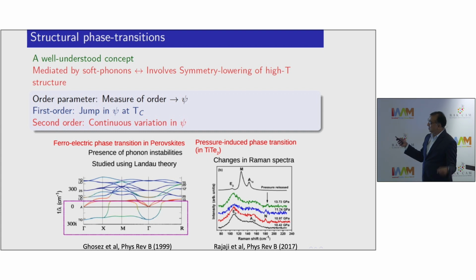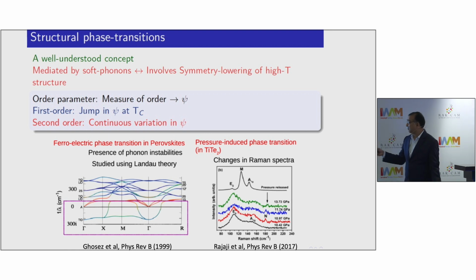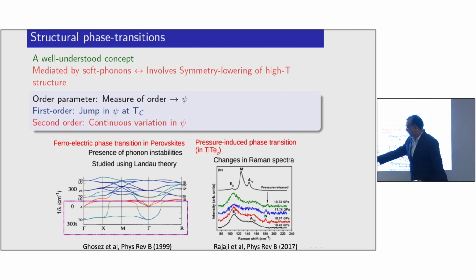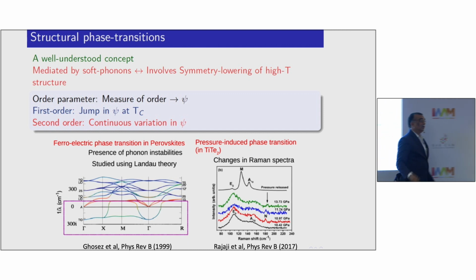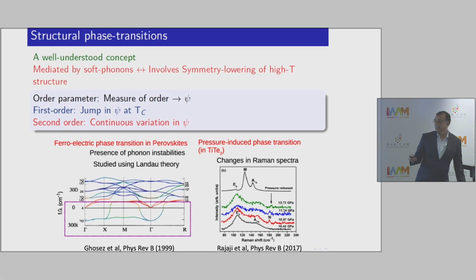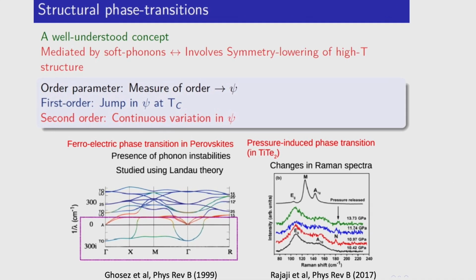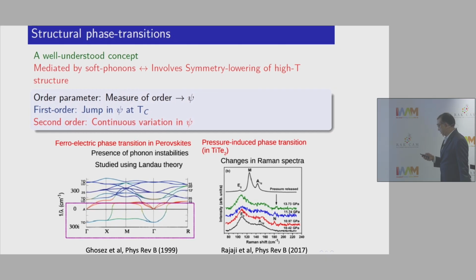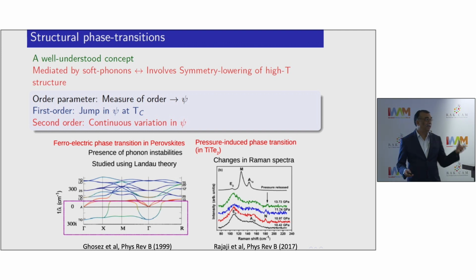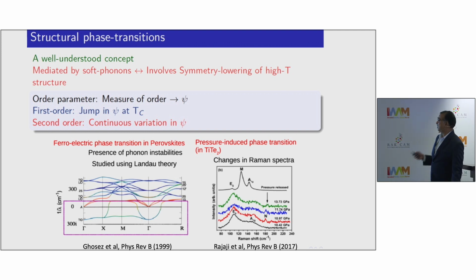If you look at very standard structural phase transitions, I'll quote here the ferroelectric phase transition, you will find there are unstable modes, which have imaginary frequency, meaning omega squared is negative in this case. Those constitute the signature of structural instability, which gives rise to a structural phase transition. And in experiments, of course, you will also see anomalies in those specific phonons when the phase transition occurs at that temperature. Okay? So phonons really are the key degrees of freedom to these phenomena as well.